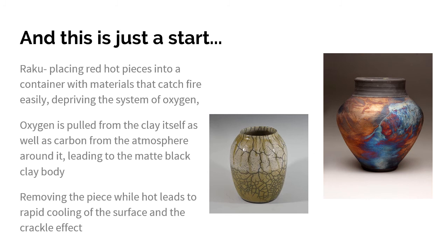And there's the Eastern Japanese style and the Western style. I've done the Western style firing before, and basically you heat your piece to red hot and you very quickly pull it out of its kiln and you put it into a container with newspaper or wood chips, something that burns very easily and pulls the oxygen out of the atmosphere. So raku is in that reduction state with a lot of carbon monoxide, a lot of carbon soot, and oxygen is pulled out from the clay body itself. Carbon from the atmosphere of the kiln is deposited on the piece. And so raku has this black coloring wherever it is unglazed in the final clay body.